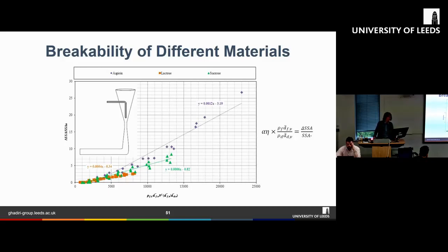Instead of looking at fractional mass loss, we now look at the shift in the specific surface area of the material, and then plot it against the density, particle size, and velocity. We then get this type of correlation. You can see that here we've got three different types of material: aspirin, lactose, sucrose. The slope of this line gives us a measure of the breakability of the material. And looking at here, you can tell that aspirin breaks more easily compared to sucrose and lactose.